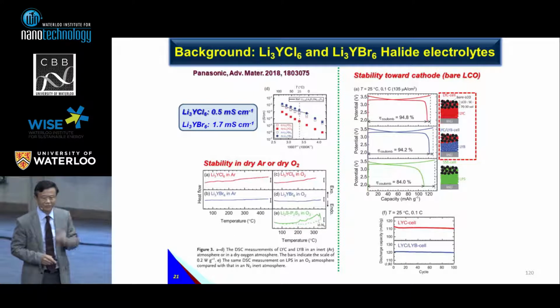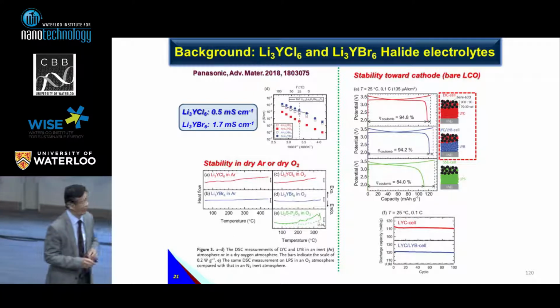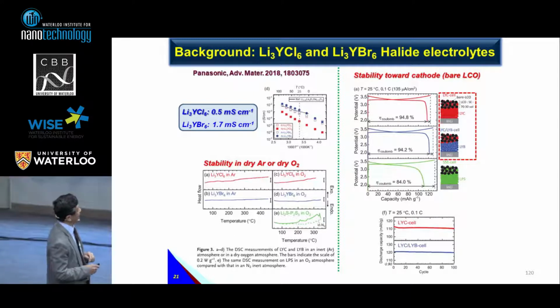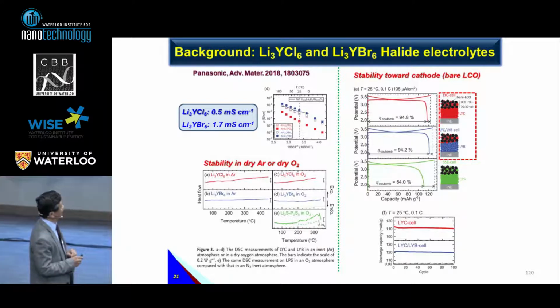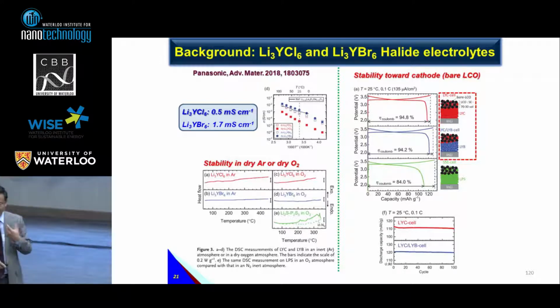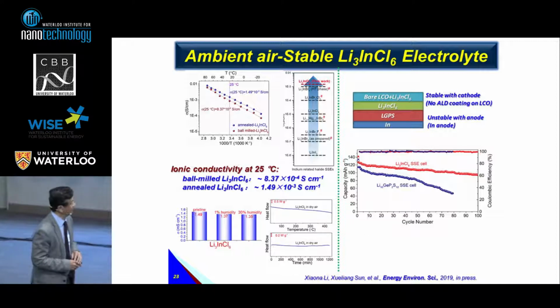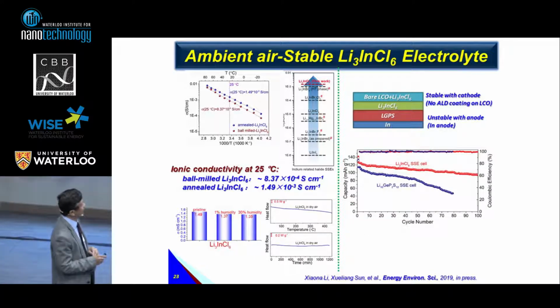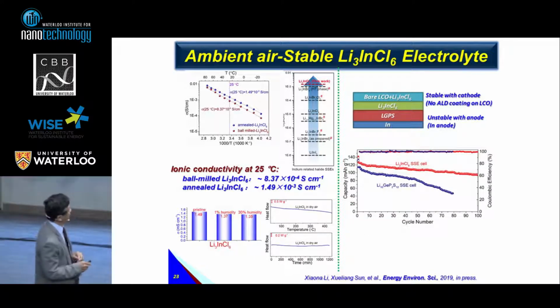Panasonic just reported last December. They found one type of solid-state electrolyte with a very high ionic conductivity, and also very good performance for solid state, with the cathode being quite stable too. So we also work on that system, halide-based. Recently we found a higher ionic conductivity. The lithium indium chloride has very high ionic conductivity and is also very stable in the environment.